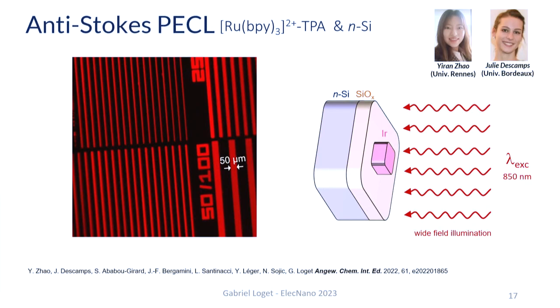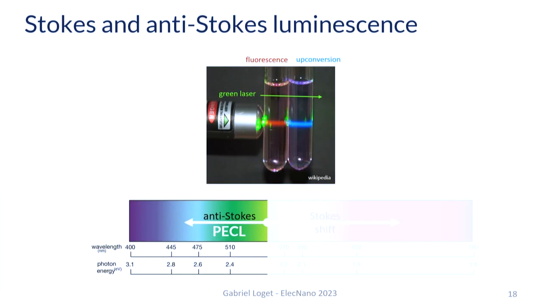You see on this very nice microscopy picture that was obtained by Julie in Bordeaux that indeed it works. So here we have several widths of iridium bands from about 10 micrometer to 50 micrometer. And you see here that indeed this pattern is revealed. So this shows that PECL is occurring locally.